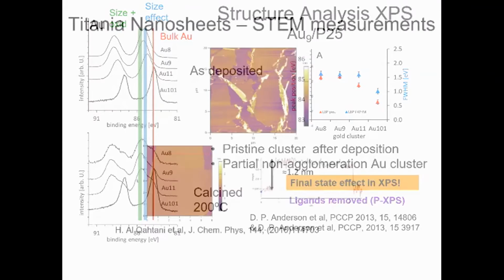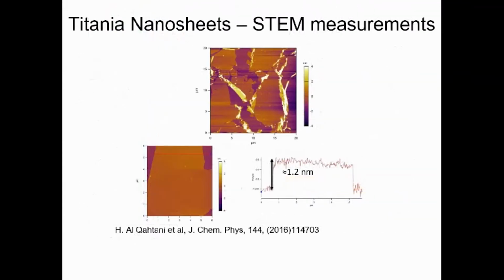And we move to the STEM, the scanning transmission electron microscope. First, we deposit them on oxide, as I mentioned, to increase the catalytic activity of our gold nanocluster. We start with the unique titania nanosheet, which is special to the NIMS Institute, where we have just a single layer of nanosheet with a huge lateral range, and we deposit our gold cluster. The thickness of this sheet is exactly 1.2 nanometers.